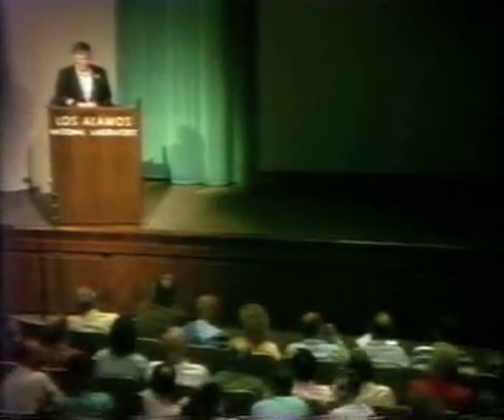Can you describe a little more about the experiment that failed and what you observed when that was concluded and what you did to analyze the results and what you think? Which experiment is that now? The one that vaporized or self-destructed? It was a bit of a mess, to say the least, but that had been running for several months, and we decided to start doing the thermochemistry, so we wanted to turn the cell off. So we turned it off too quickly, and several hours later that accident happened, and it vaporized 90% of the cube and the bottom of the vessel and some of the surrounding materials and equipment in the hood.